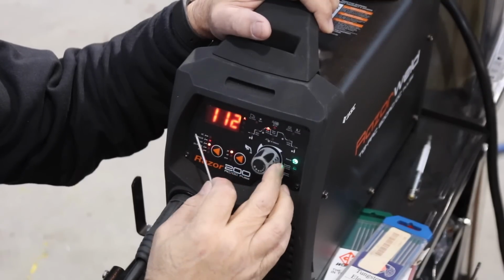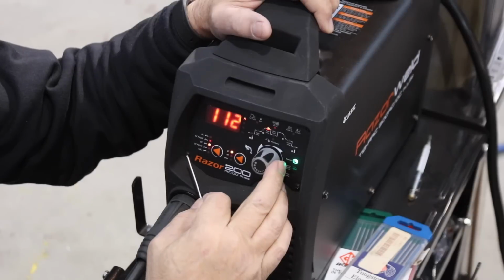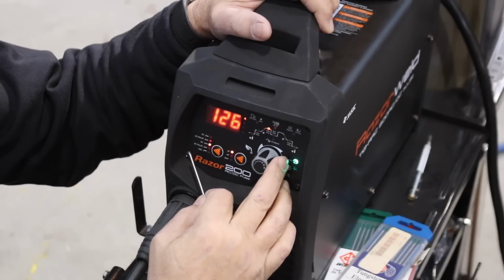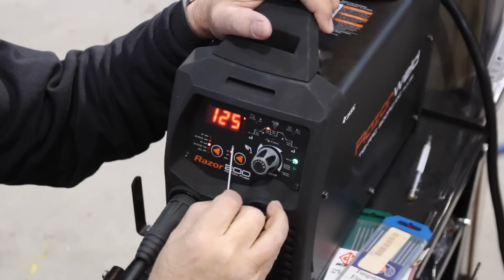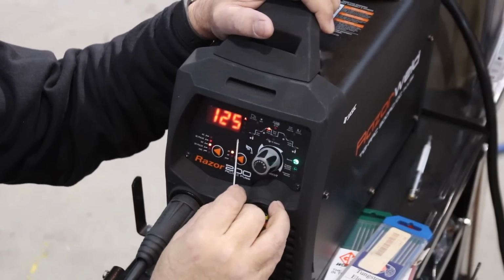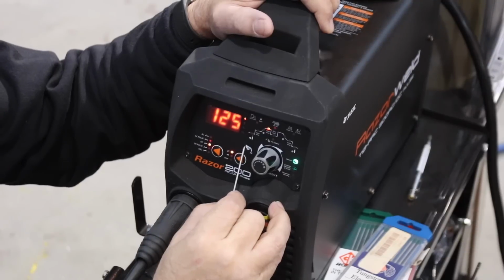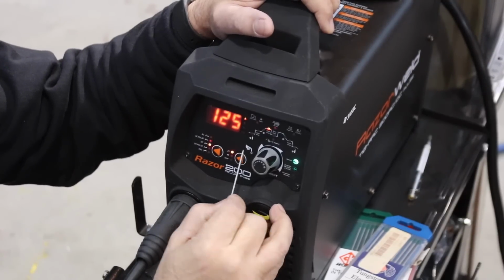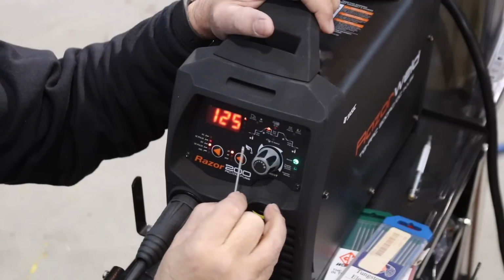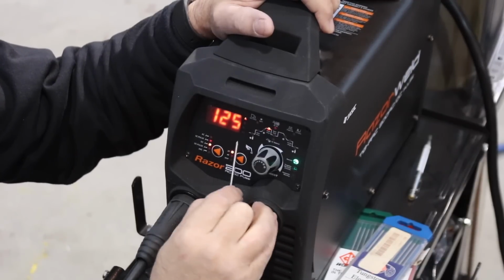Operating amperage, again, is about 1 amp per thousandth of an inch for carbon steel, up to 1/8 of an inch. After that, you start needing a little bit less amps. You can almost weld anything, no matter how thick, at probably 175 amps just doing multiple passes on steel. Not on aluminum, but on carbon steel.